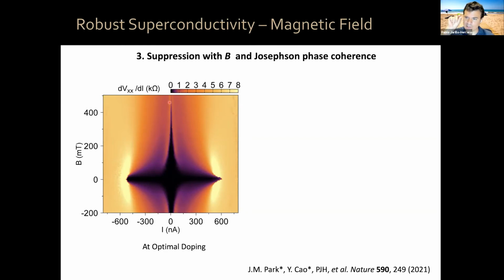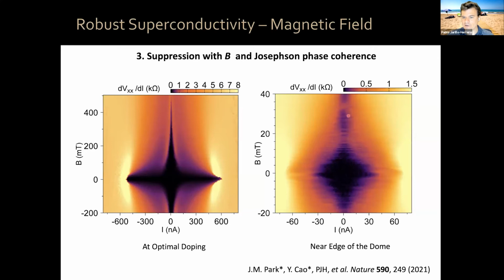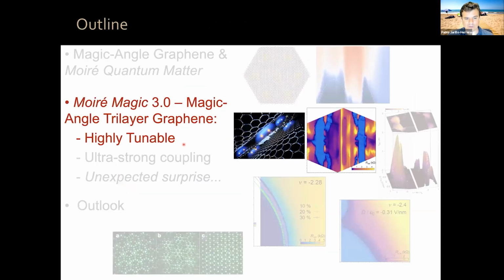If you now tune electronically your system to the boundary of the superconducting dome, where the system is barely superconducting, the system tends to divide itself into superconducting and non-superconducting islands, which can give rise to Fraunhofer-like oscillations. Meaning that there's just some phase coherence in your system. So this unambiguously proves that you have a superconducting system. Now, let me show you that this is a very highly tunable system.